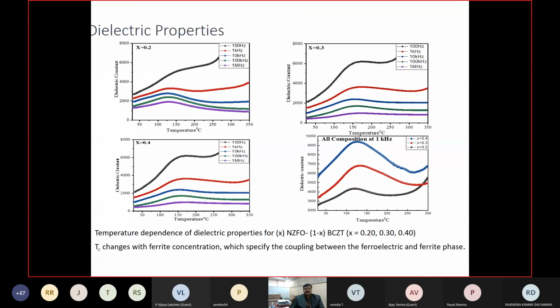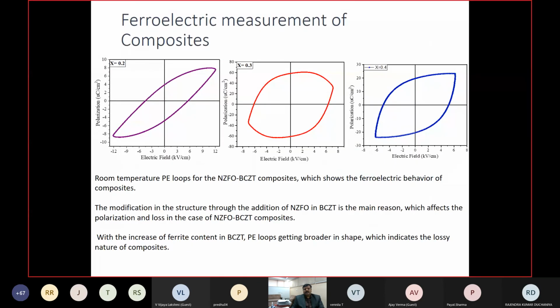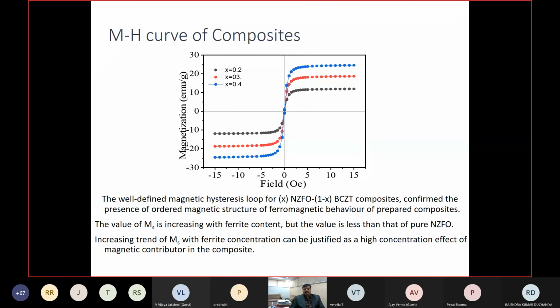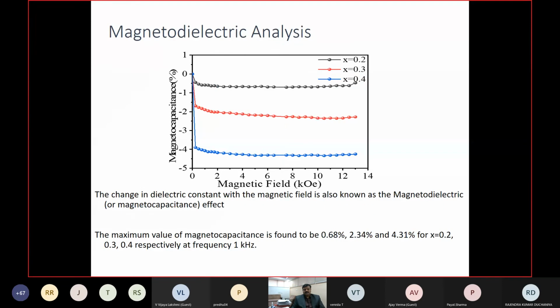So she took the dielectric properties of the composites. It shows a very good dielectric constant for x equal to 0.4, nearly 9,000. Then these are the ferroelectric loops. For x equal to 0.4, it is showing a lossy loop. For x equal to 0.2, it is showing some good behavior. Then these are the composites' MH curves. You can see that the magnetization reduced from 60 to nearly 25 because the ferroelectric component came into the picture.